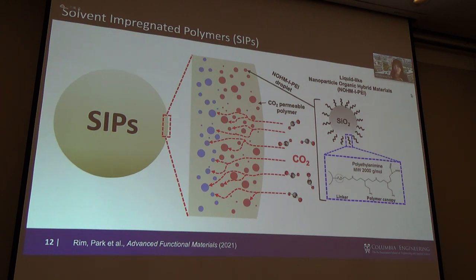Basically, instead of using a microfluidic device, we directly add our highly viscous NOHM-I-PEI solution into the UV curable polymer, and use high shear to make a micro-emulsion of these two mixtures. And then we put this micro-emulsion onto a flat surface, and then we can UV cure afterwards. By doing so, we were able to really make sub-micron droplets, or in some cases nano-droplets, of these materials in highly permeable gas solid substrates. And it worked really well.